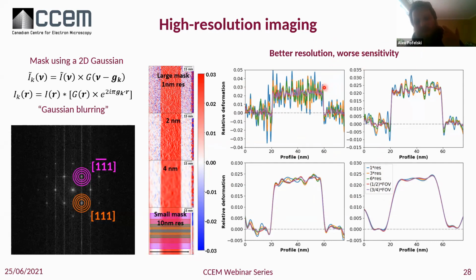And this seems absolutely weird. Why would this completely change regarding the size of the mask that you are using? This is related to the noise that you have in your data. Because you have noise and you are using this type of Gaussian blurring, the Gaussian blurring helps in averaging the noise. This is specific to this processing method that we are using here, something we didn't have in the real space method just before. Here we have this interconnection between the experiment and the processing, because if there were no noise, this Gaussian mask would have absolutely no effect. So that is the first key in trying to improve your data based on the processing method that you are using. Something also to keep in mind when using the GPA.